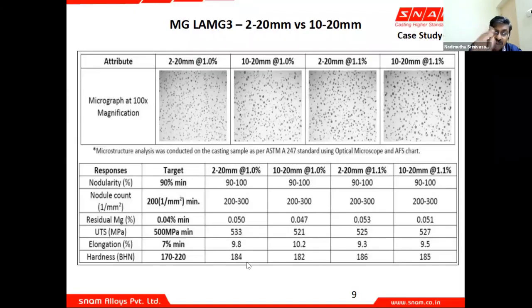Now this is for one grade, and interestingly for you, a 10 to 20 mm at 1.1% and a 2 to 20 at 1% had similar results. So you can see that a reduced usage of magnesium alloy is very much possible.